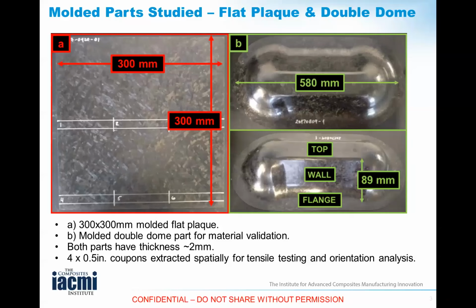Whereas the challenge with composites, as we know, whether it's continuous or discontinuous, is that the orientation of the fiber at a given point controls everything, and it becomes even more critical for discontinuous systems. So the properties you generate on simplistic flat plaques will not translate to the real components that most of you are interested in.